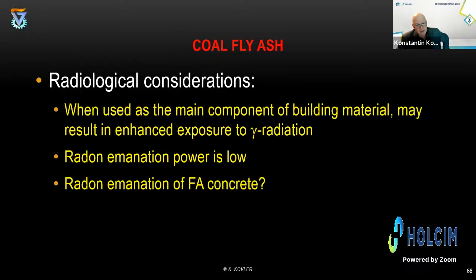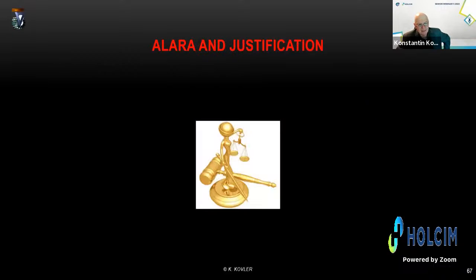Maybe you heard about the uranium chain, and radon is one of the products of the disintegration of uranium-238, immediately standing after the precursor, radium-226. And then radon is a very important contaminant for the indoor air. By the way, maybe you know that most of the radiation dose from natural sources is coming from radon, indoor radon. And very fortunately, radon emanation, so the amount of radon exhaling and emanating from building products, is very low. Why? Because coal fly ash is just very dense particles made of glassy phase, produced under very high temperatures in thermal plants. And it is very difficult for radon to escape this glassy phase into the surroundings.